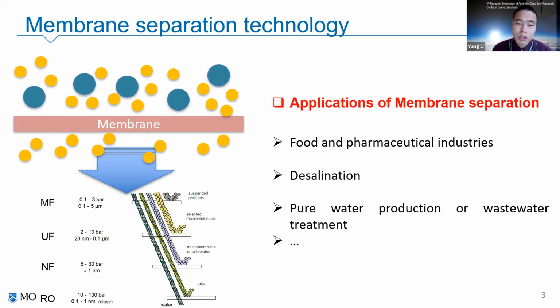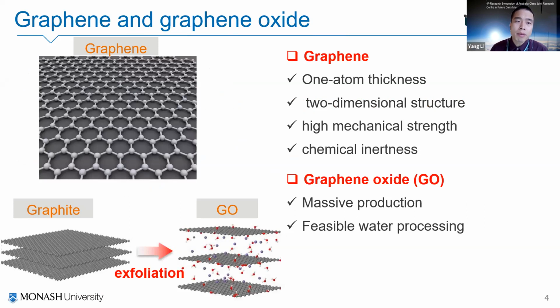Fundamentally, membrane separation is according to the sieving effect. For different membranes, such as microfiltration, nanofiltration, or reverse osmosis, the pore size is quite different from each other. And the separation basically comes from the charge and size exclusion effect. As the development of membranes highly relies on materials development, graphene has offered an alternative choice for nanofiltration membrane materials, as graphene is a very thin material, around 1 atom thickness, with a 2-dimensional structure, very high mechanical strength and chemical inertness.